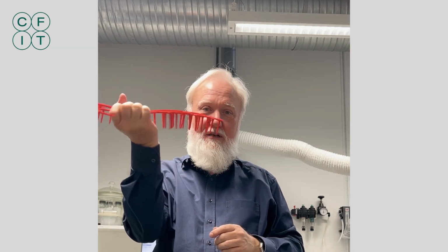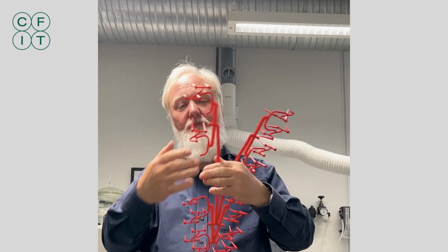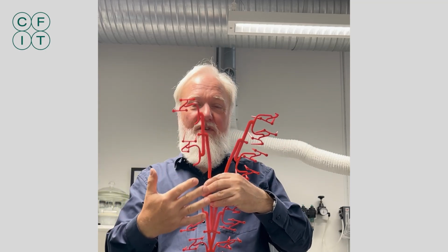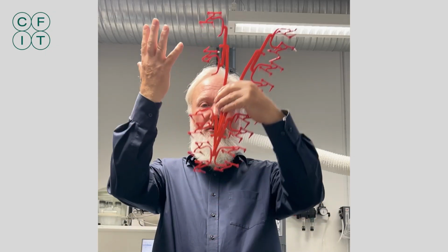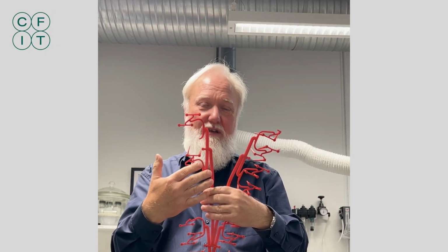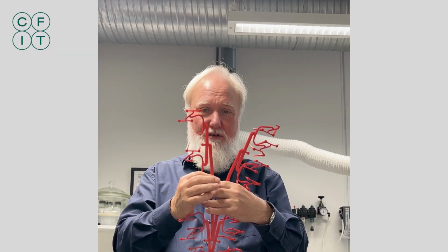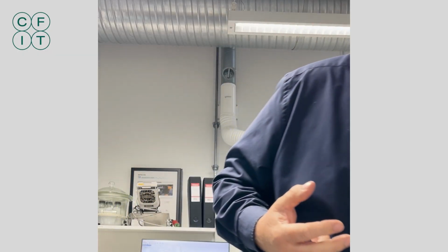So this is a lot of thermal exposure to this material. But for real production, it's not the small ones. We are talking about inlets at this size. And here we have challenges both because it goes to the molding machine a lot more times because it's much bigger than the parts. And we are also filling the inlet system very, very fast to make the polymer really flow easy. Then you have shear heat, meaning you have local heating at very high temperatures in these systems. So that's two challenges. You have the repeated molding and you have the shear heat in the runner systems.